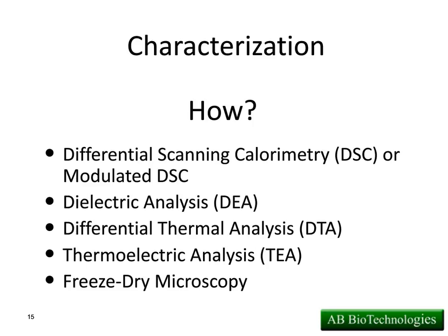I won't say anything about these other techniques, just in the limitations of time that we're going to have, but these have been used in the past, again, with decent results. But if you're going to be doing this and you want meaningful information, the DSC is going to be the technique of choice. We always back that up with freeze-dry microscopy. These two techniques give slightly different supportive information that really gives us the complete thermal picture of our sample, so we know exactly how it's going to behave as a function of temperature during freeze-drying.